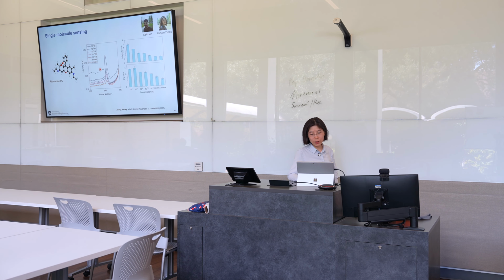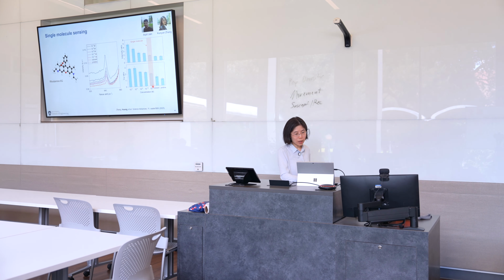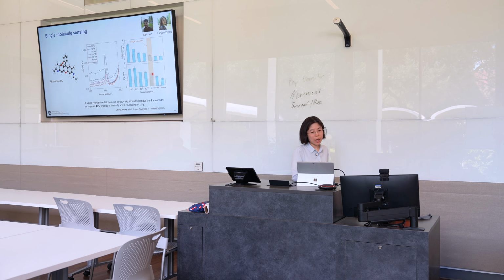All right, so now if we summarize the intensity of these modes and 1/q factors, we can see they change monotonically with the molecule concentration. In particular, this 10 to the minus 12 molar corresponds to a single molecule under the optical beam. So that means we can detect a single rhodamine 6G molecule. Not only that, compared to the pristine sample, there's already a significant change for the mode intensity and also in particular this 1/q factor. We have seen 43% change of mode intensity and 78% change of 1/q factor with just a single rhodamine 6G molecule. So this is a very sensitive probe to detect a single molecule.